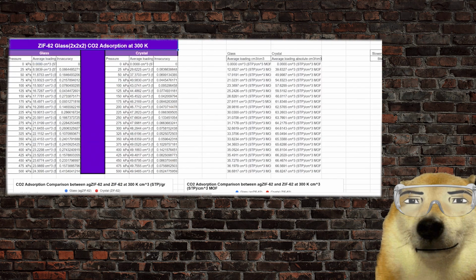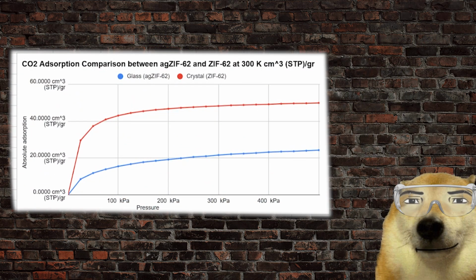Now, applying this to both crystalline and glassy ZIF-62, we can directly compare their performance. The first major result is straightforward. Both follow a similar trend, but the crystal consistently absorbs significantly more CO2 than the glass. The reason is structural. The crystalline MOF has a much larger accessible pore volume, which gives more space for gas molecules to occupy. In other words, pore size is the dominant factor.